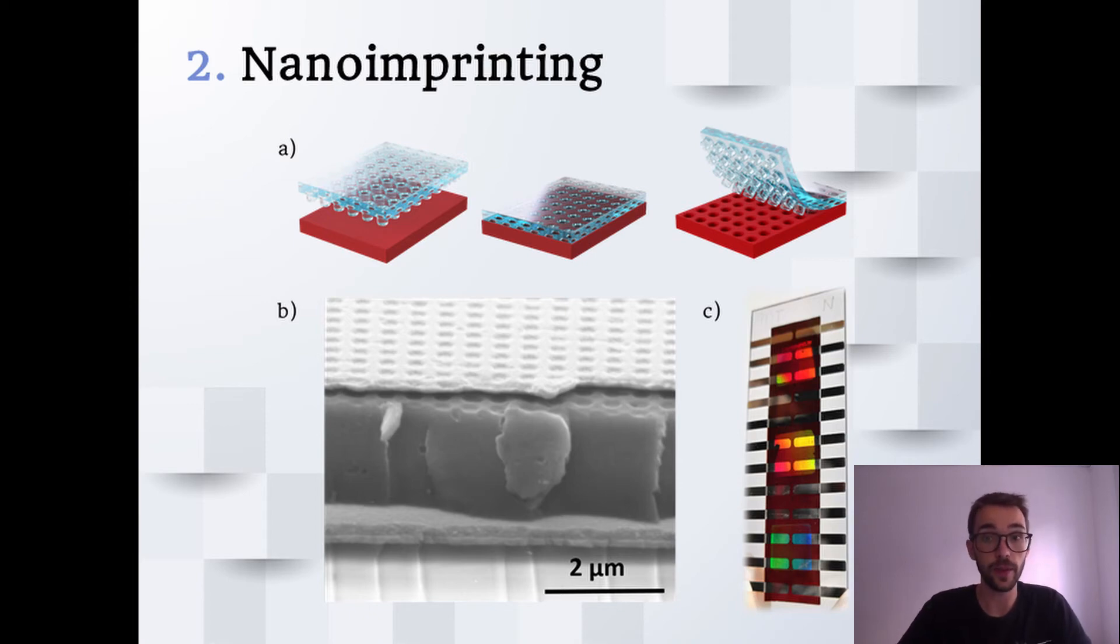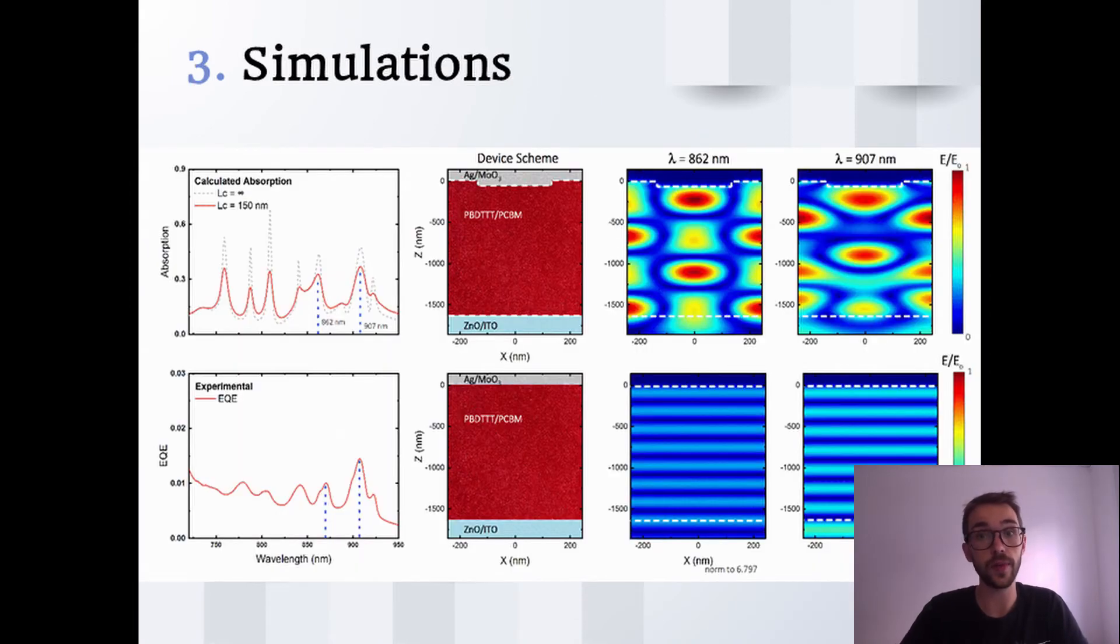We also simulated the absorption increase that this structure would have, and we saw that when compared to planar devices, the electric field strength was up to six times stronger with a nanostructure of only 60 nanometers in depth.